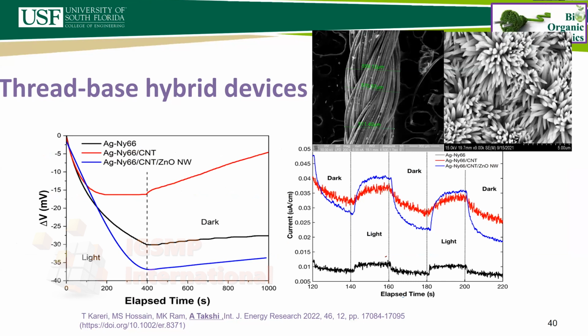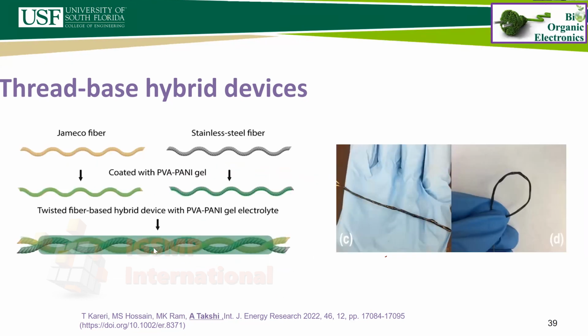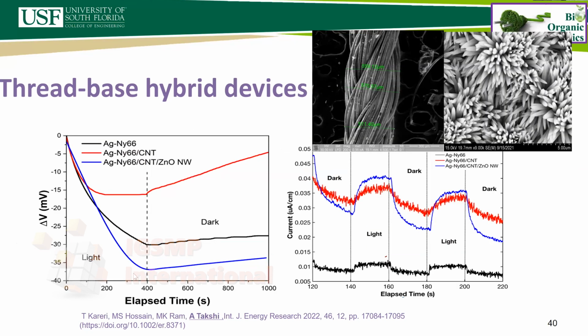And of course, we figured out that if we coat one of the threads with some sort of metal oxide, such as zinc oxide nanowires, we are able to improve the energy conversion efficiency in the devices. This is a very recent result from a very recent publication that shows that just by putting the gel between the 2 threads and then twisting them together, you can make a hybrid device that generates some voltage, and when it's dark, it still can maintain that stored charge.